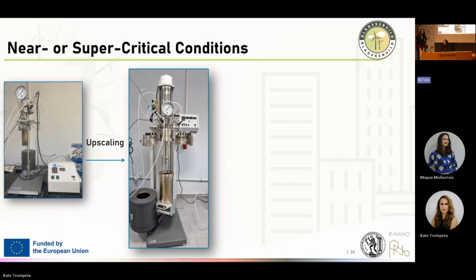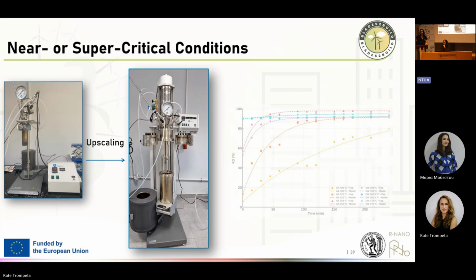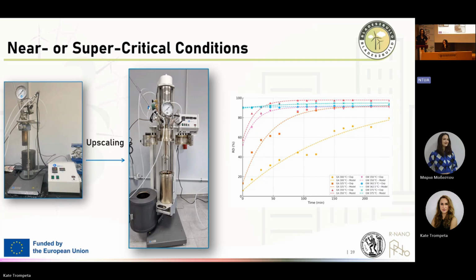In order to have a supercritical solvolysis, we need very expensive equipment, as I said. Here we can see a high pressure, high temperature reactor that can withstand up to 350 bars. The first reactor is a 100 milliliter reactor, and the next one is a 4-liter reactor. What we have seen is that when we test and calculate the kinetics in the small reactor, we don't have the same result in the big reactors. So in our big reactor, the kinetics change. That's why the upscaling is different and more difficult, because we don't have the same energy demands, the same time, and the same temperatures and pressures needed in the small reactor to have the same results.